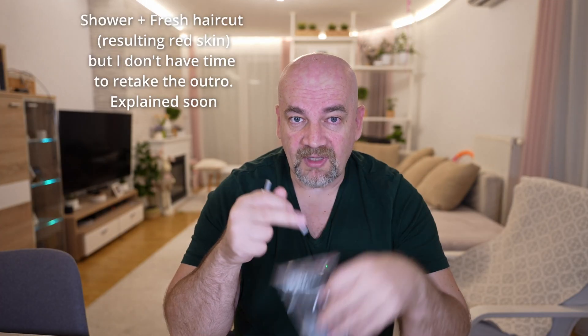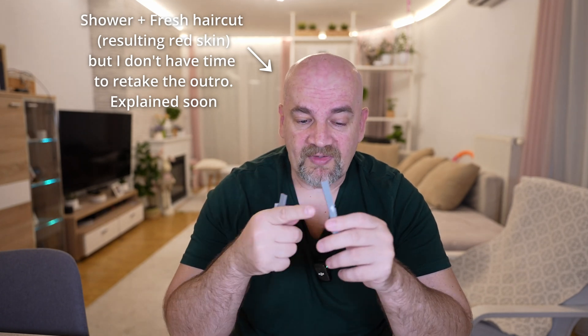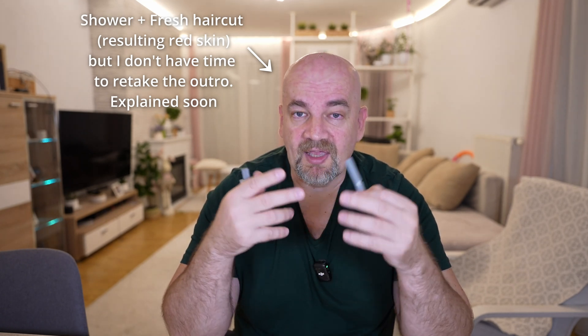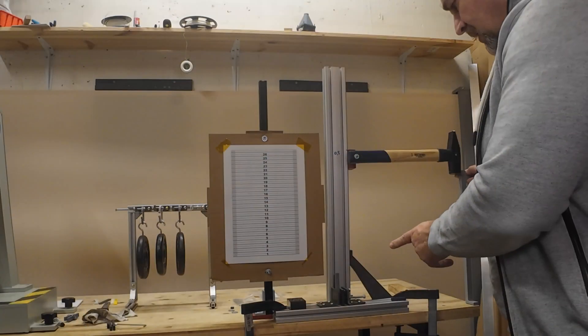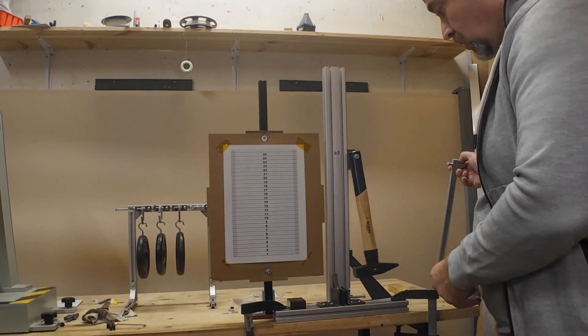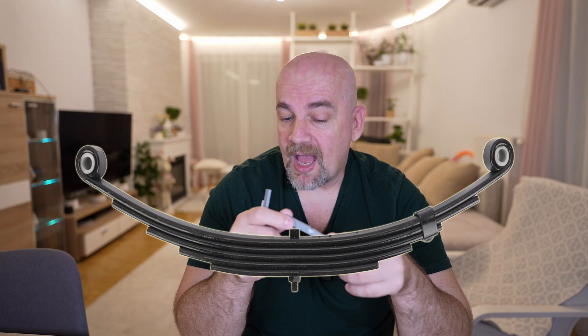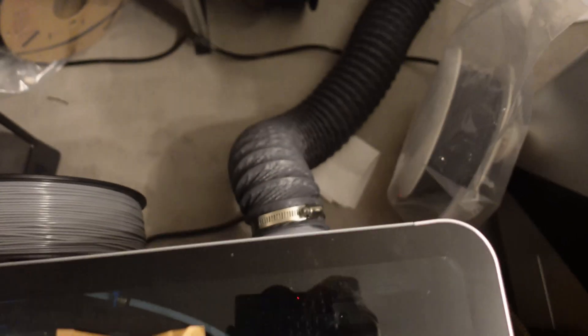Now conclusions. First about the materials, then I will have some messages to companies. First about this ABS. It has the mechanical properties of average ABS material with fantastic impact resistancy, but on the other side a little bit weaker layer adhesion. I already noticed this several times—maybe this weak layer adhesion results in better impact resistancy, some kind of leaf spring effect. I'm not sure, I have to investigate this deeper. Also I noticed a little bit stronger smell with this ABS, like those old regular ABS materials. Because nowadays I tested mostly those other less-smell ABS or ASA materials, and compared to them this is stronger smell.